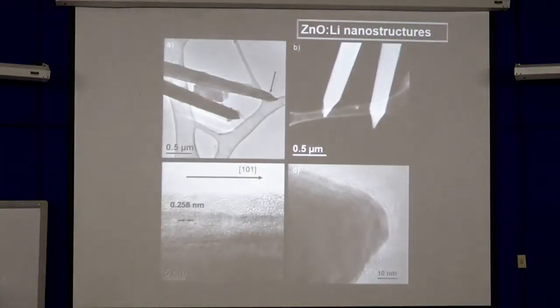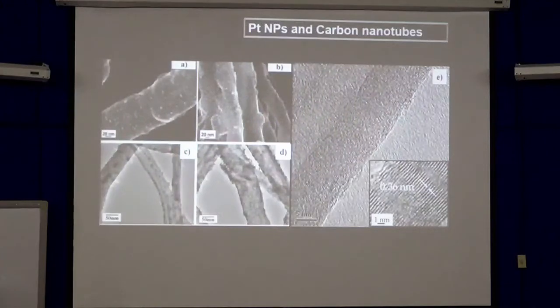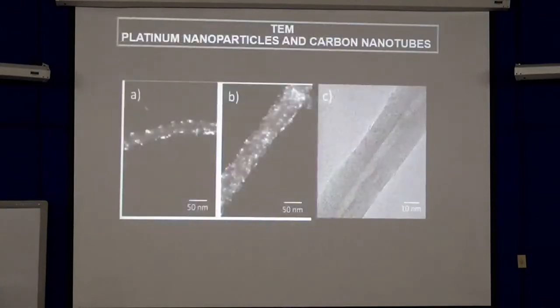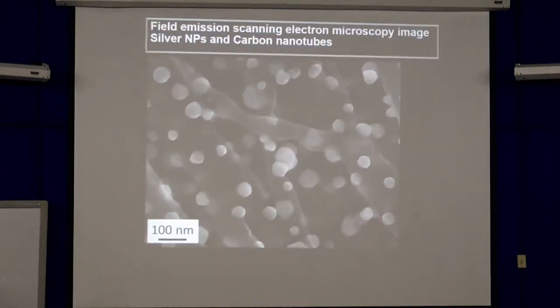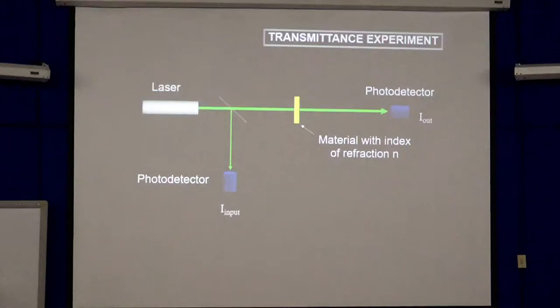These are lithium doped zinc oxide. And in our group we also prepare carbon nanotubes. See, these are carbon nanotubes, and we put nanoparticles in order to control signals. This is another image. I think the platinum nanoparticles are the bright points in the image, and silver nanoparticles. Okay, now about the experiments.